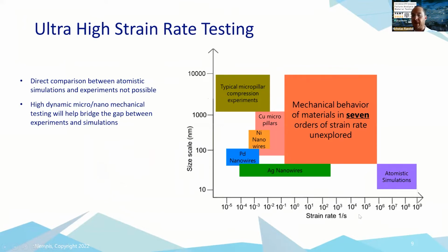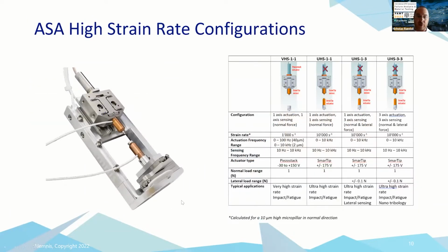And we do that by being able to deform very quickly, typically using a piezo mounted here that can deform the indenter at up to 10 millimeters per second. And we do that on a very small pillar, which is a few microns. Therefore we can get up to strain rates of 10^5, so 100,000 per second, the speed almost of a bullet hitting something, right? So it's ballistic. And this allows us to map strain rates over many orders of magnitude.